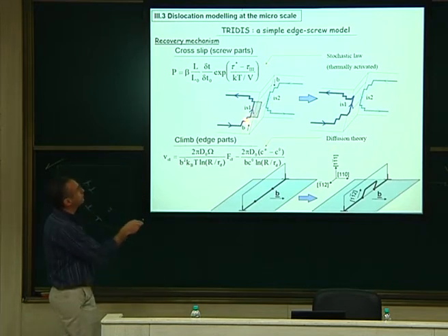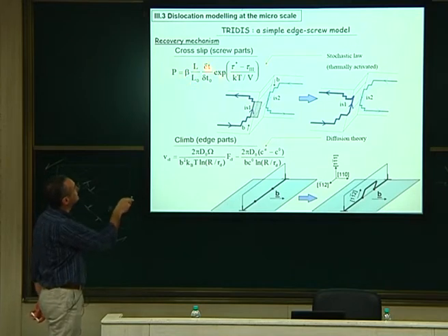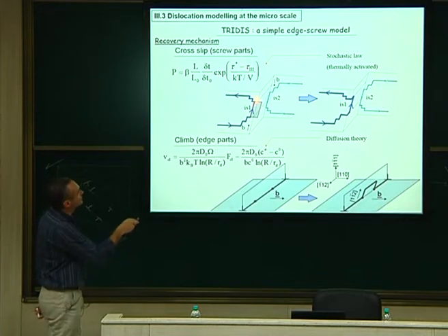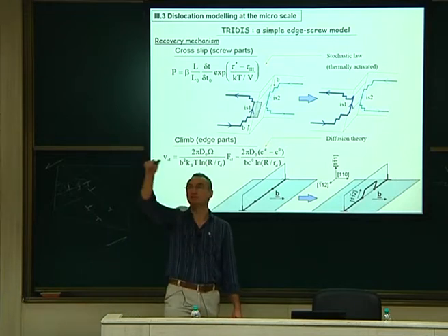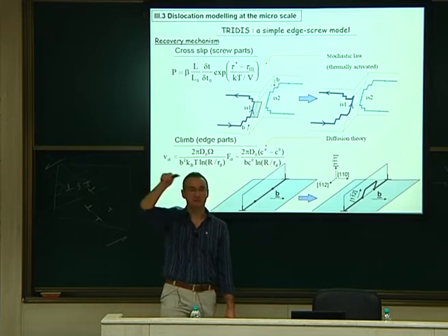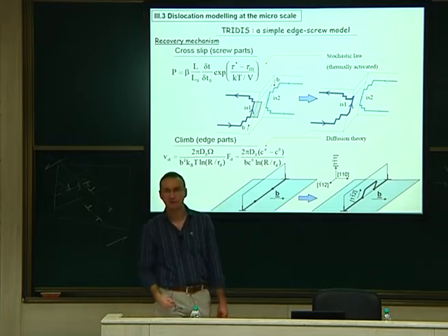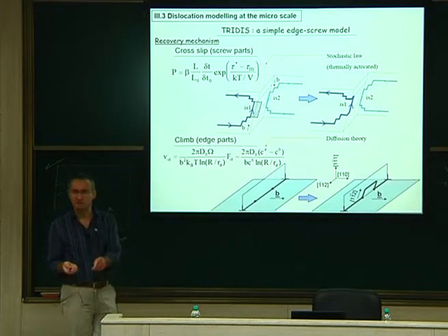To do that, we compute the probability during the flight of this dislocation segment. This is the flight. For this to happen, the probability depends on the length of your segment, the waiting time there, and the temperature. And here you have the stress out of the plane and the mechanical macroscopic stress that we defined yesterday as the start of the third stage: stage 1, stage 2, stage 3. So at stage 3, we assume that there are a lot of cross-slip events occurring, so we put it here. This value I don't like much.